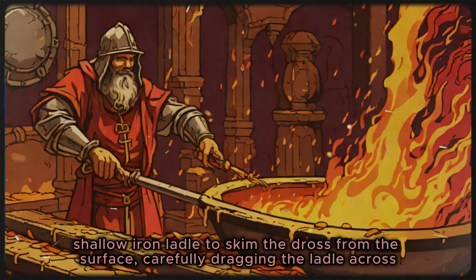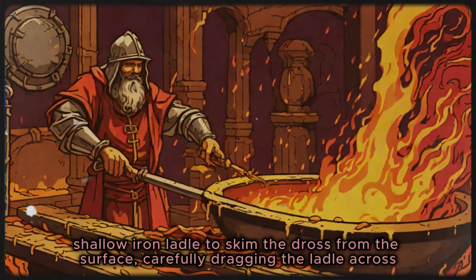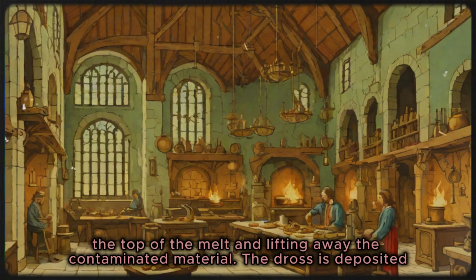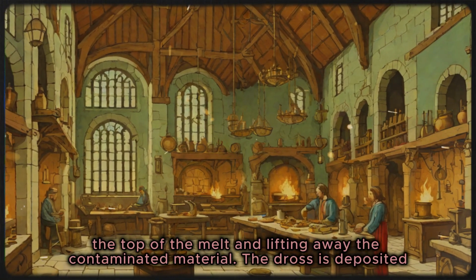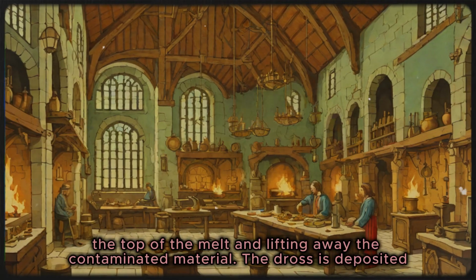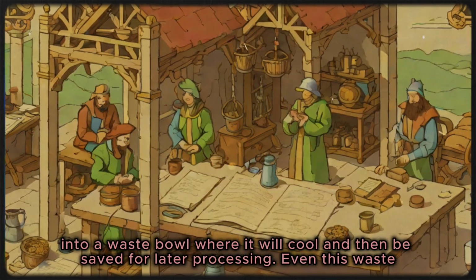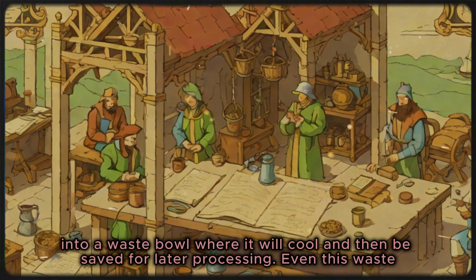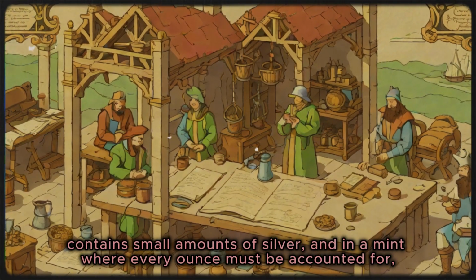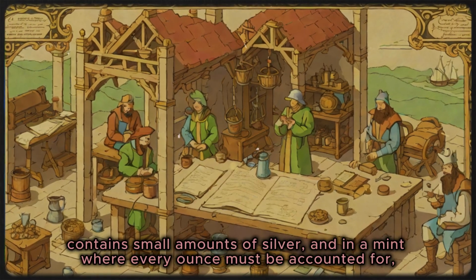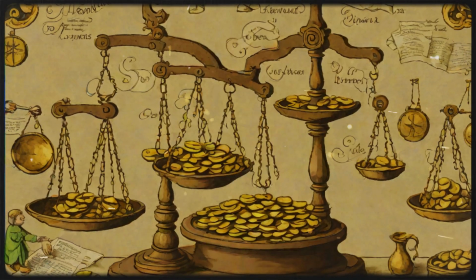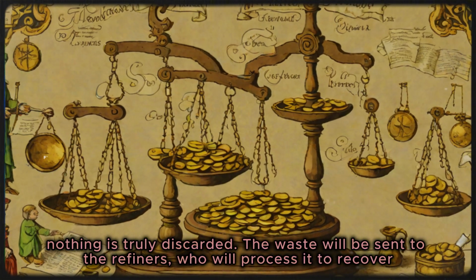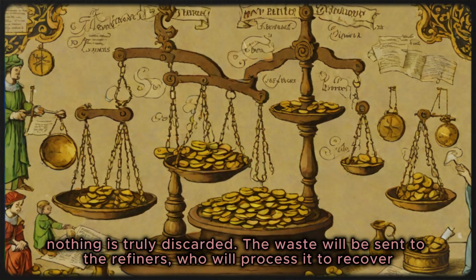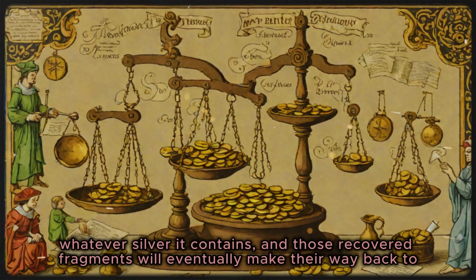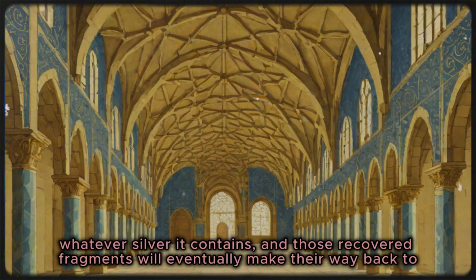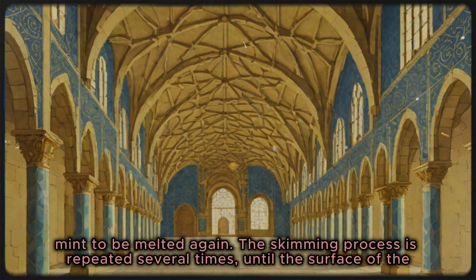The moneyer uses a shallow iron ladle to skim the dross from the surface, carefully dragging the ladle across the top of the melt and lifting away the contaminated material. The dross is deposited into a waste bowl, where it will cool and then be saved for later processing. Even this waste contains small amounts of silver, and in a mint where every ounce must be accounted for, nothing is truly discarded. The waste will be sent to the refiners, who will process it to recover whatever silver it contains, and those recovered fragments will eventually make their way back to the mint to be melted again.